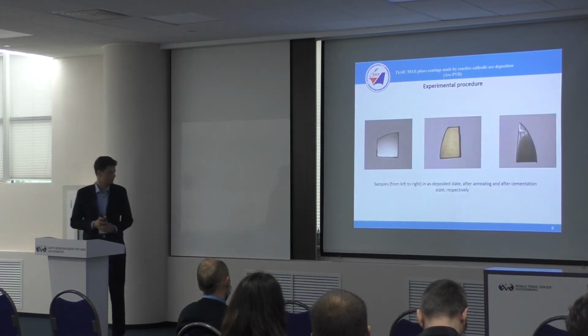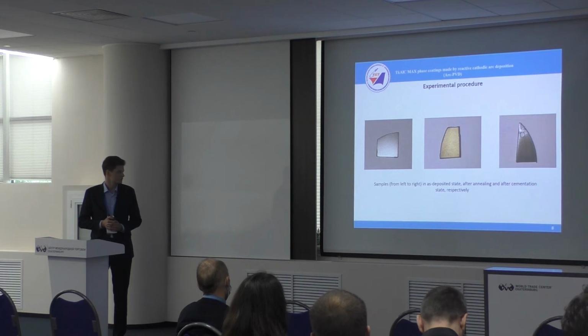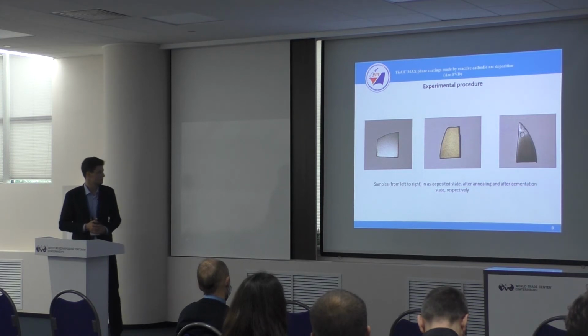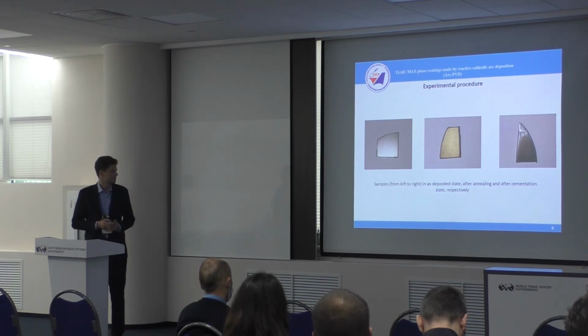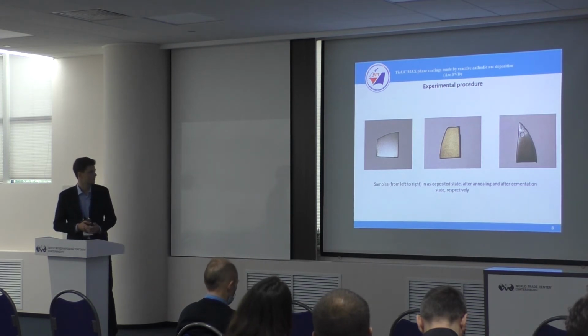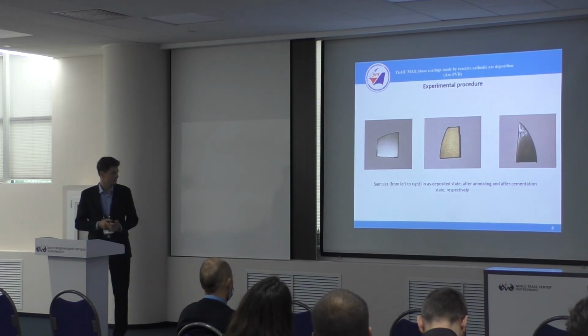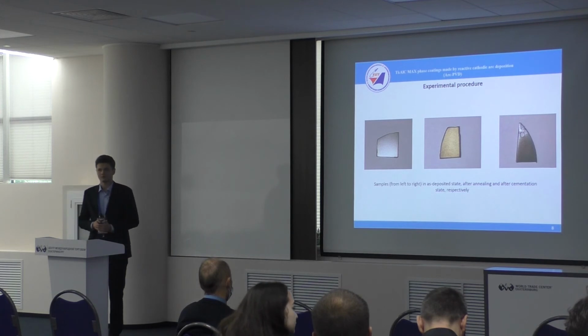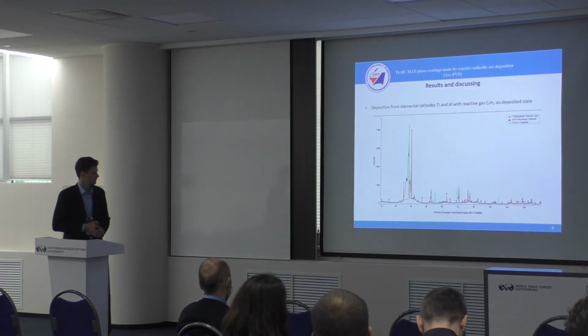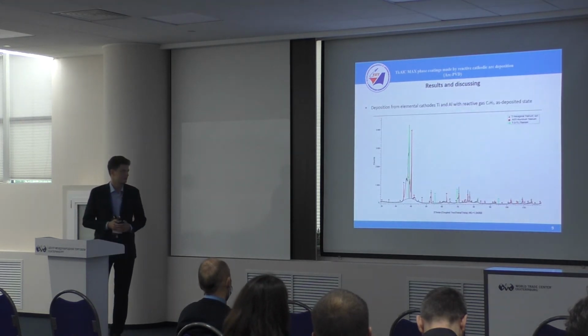This is a visual examination of samples after deposition. On the left picture you can see the as-deposited sample. In the middle you can see an unusual yellow annealed sample, and on the right picture you can see a sample after cementation. Let's take a look at the X-ray analysis.